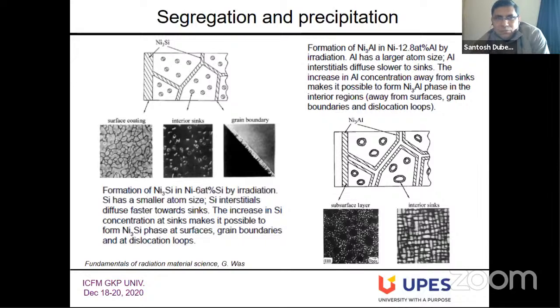Segregation is one more process which can lead to loss of certain material properties. And if the segregation happens to a significant amount, above the solubility limit of that component in the matrix, you'll have formation of precipitates and so on.